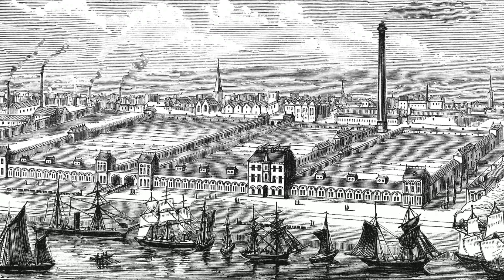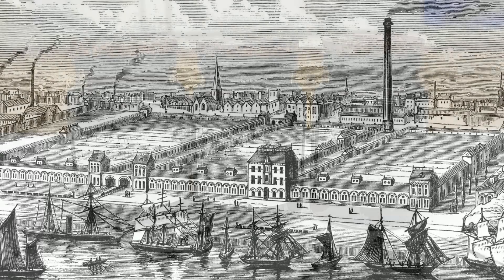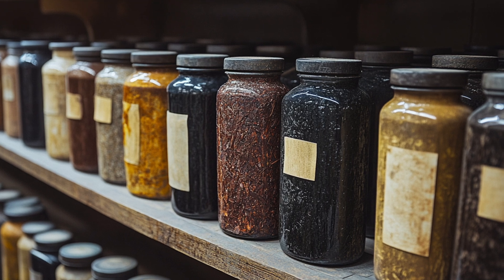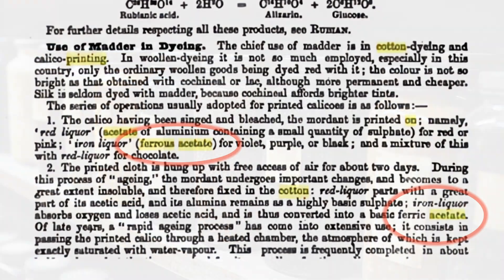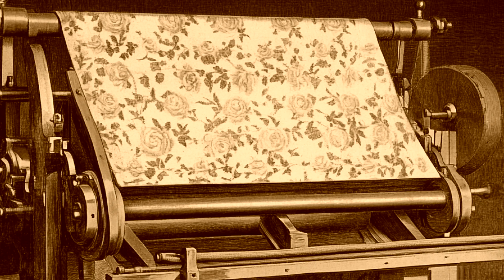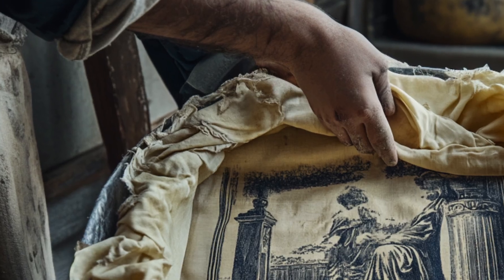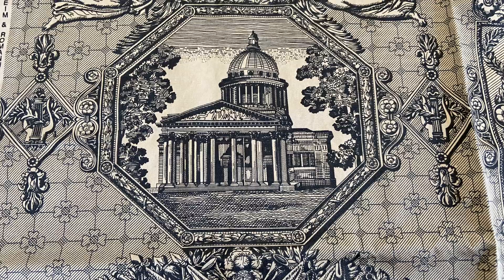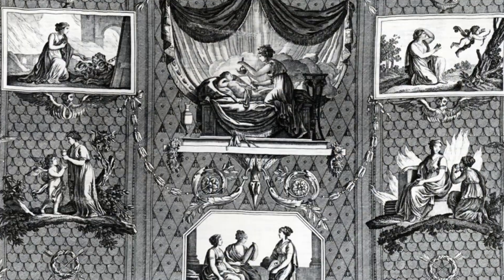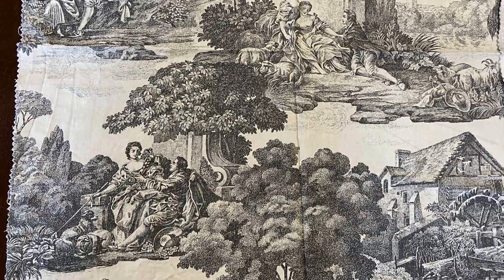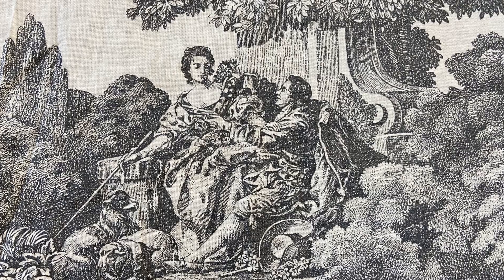In Europe, the tradition of black dyers also has deep roots. Various iron-based solutions were utilized, including those derived from metallurgical slag or metal shavings collected from sharpening stones. At the Gobelins Manufactory in France, dyers created black ink for shading colors in dye baths by mixing rusted iron, vinegar or sour beer, and alder bark extract. By the early 19th century, iron acetate became widely used, but the initial tannin treatment was abandoned. Iron mordants were applied to washed and dried fabric, and black motifs formed directly in the dye bath. Instead of tannin helping iron adhere to the fiber, fixation depended on careful drying followed by a stabilizing bath, which insolubilized the iron compound while maintaining its ability to absorb dye — resulting in a durable black shade resistant to washing, friction, and light exposure.